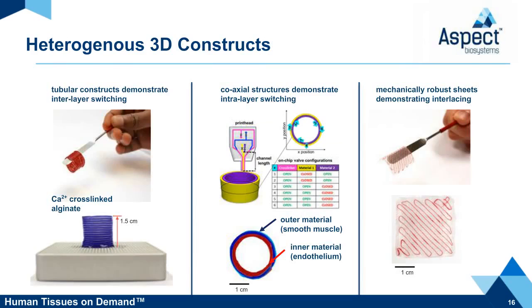Here we demonstrate a few basic capabilities of the system to generate heterogeneous macrostructures. On the far left, you can see a printed alginate tubular structure. The structure is built by switching between hydrogel inputs as the printer switches layers. The structure is reproduced with high fidelity, as the transition between one material and another does not introduce start-stop errors that could accumulate in tall structures with many material transitions. In addition, the build time does not depend on the number of switching events. This approach can be used to recreate the banded smooth muscle pattern seen in the human airway, for example.